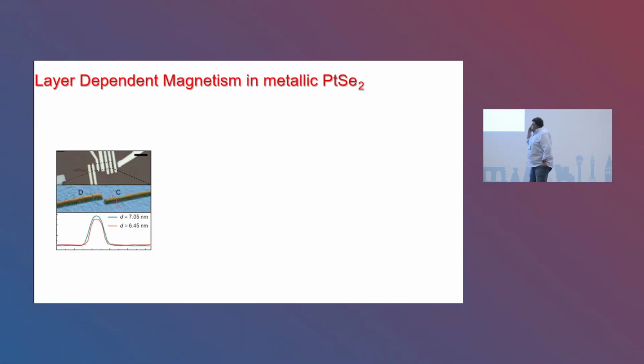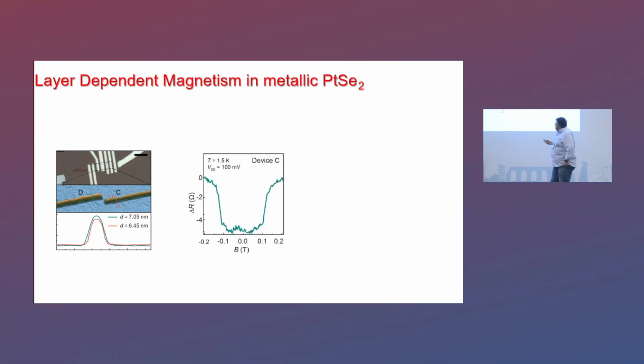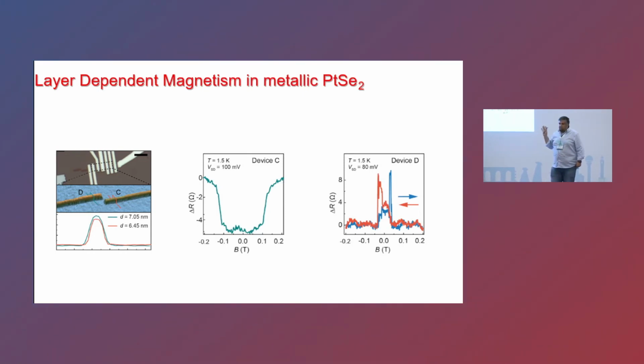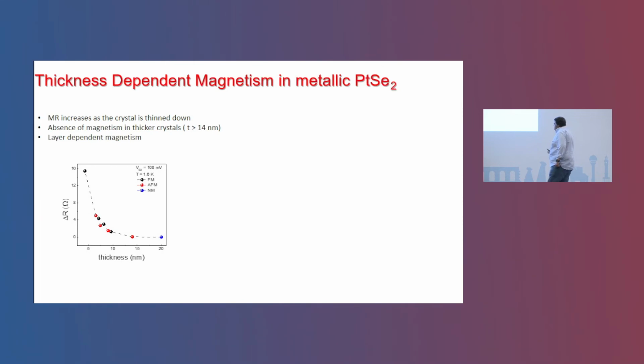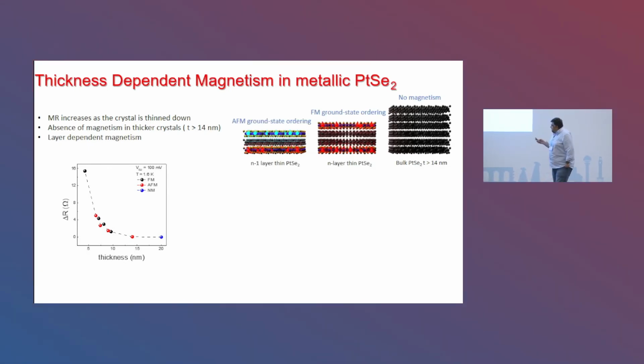And the question we tried to answer is: is there any layer-dependent magnetism in this material? For that, we compared the magnetic transport properties of two devices with a thickness difference of only 1 layer. And whenever we studied the magnetic transport properties of these devices, they were showing the ferromagnetic and antiferromagnetic response. So there was just a 1 layer difference in these crystals, and we were already seeing completely different magnetic transport behavior. And this phenomenon was only visible for crystals less than 14 nanometers. Whenever you go a bit thicker, you don't see any of these effects, and the MR was decreasing.